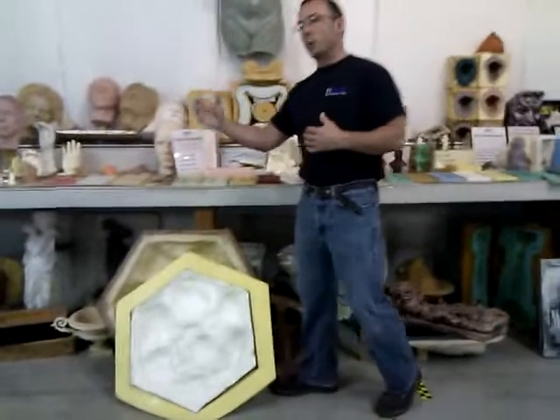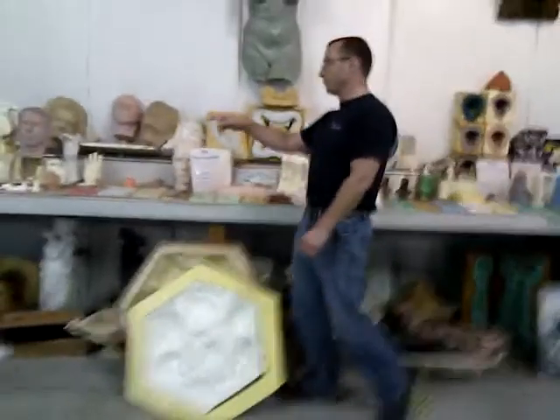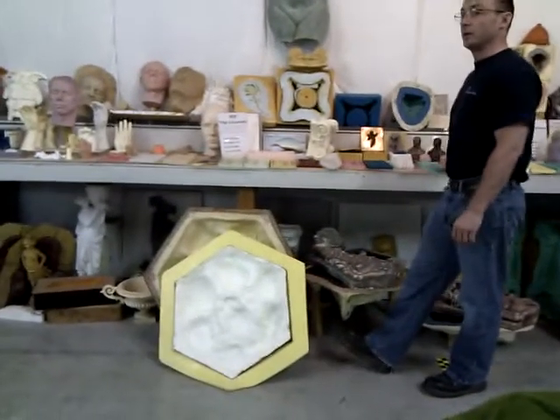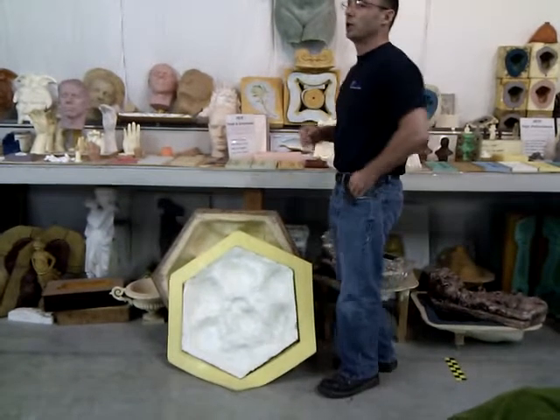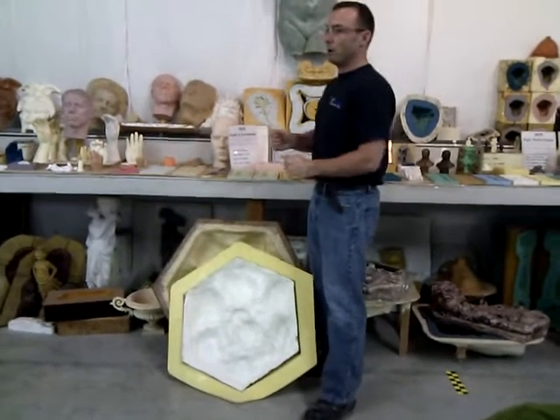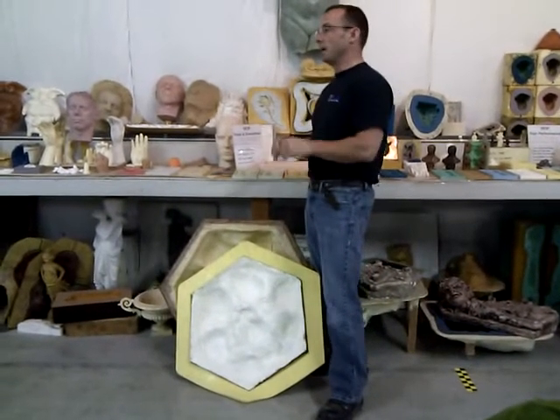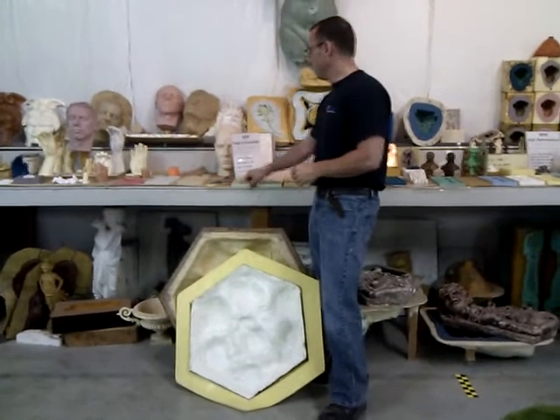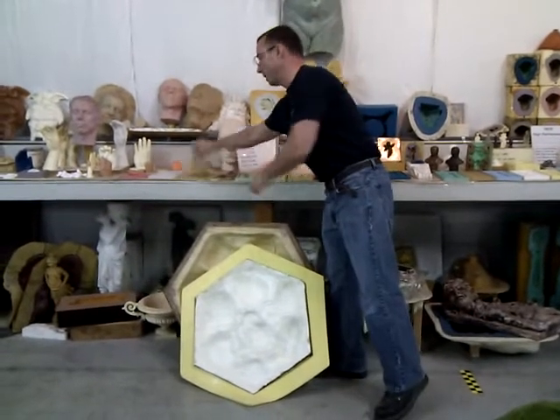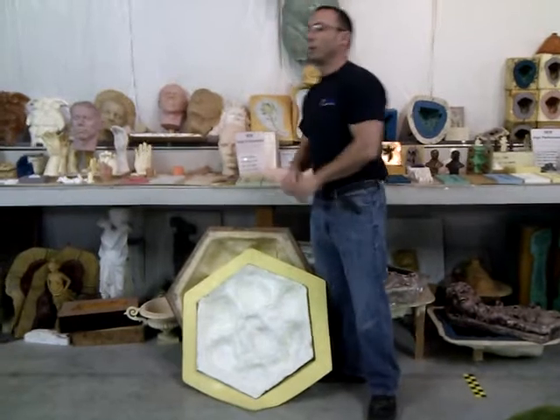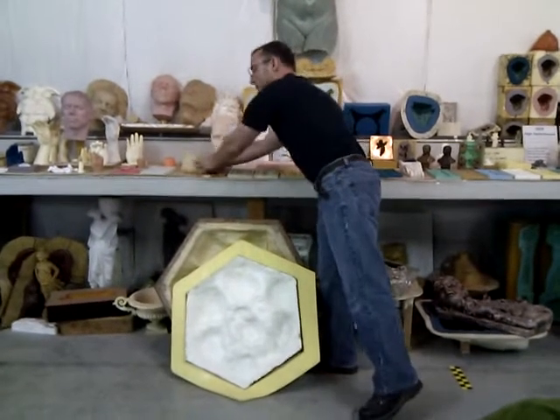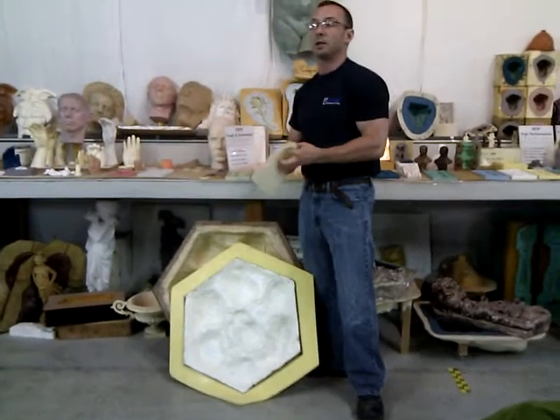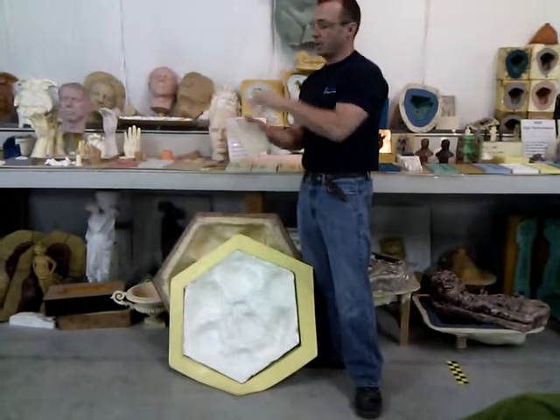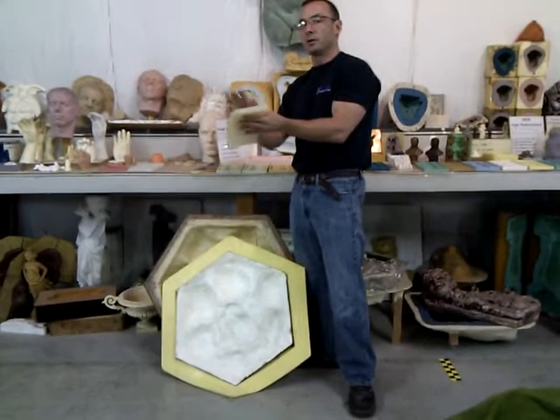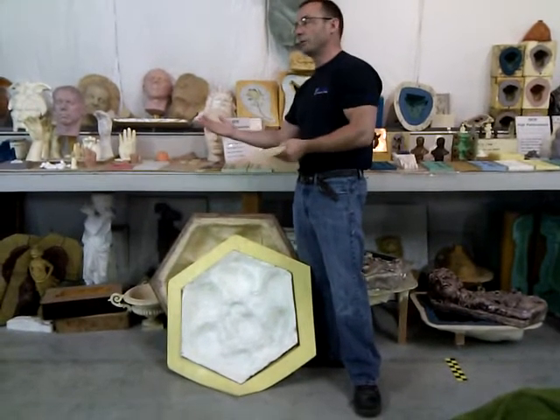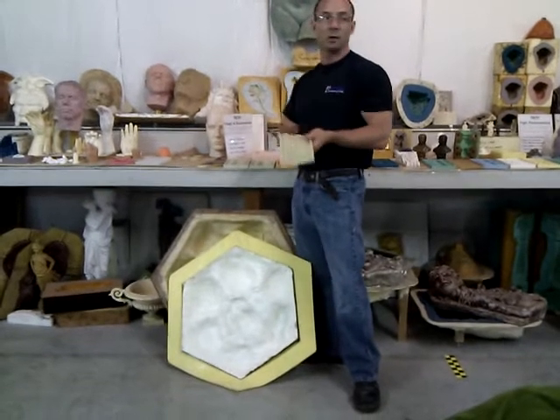The differences between the two: platinum silicones, like Platinum Gel 10, 71 series, 73 series, are very sensitive to cure inhibition, which means you pour them over a certain surface, and they won't cure. So you make a mold in the morning or at night, pour your rubber, you come back the next day, you peel it off, and it's all sticky and gooey where it contacts the model. It didn't cure. That's cure inhibition. It can't cure here and not cure here. There's a reason. Something on the surface or in the model caused that silicone not to cure.